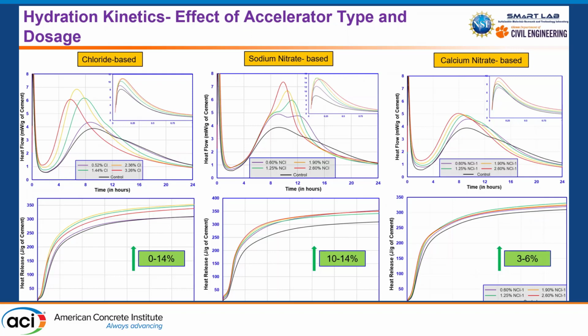So with calcium chloride based admixtures, as seen in literature, they reduce the setting time significantly, or the main silicate peak onset significantly, and they increase the height of the main silicate phase. But what happens is after a certain dosage, you stop seeing this secondary sulfate peak. That is because there are a lot of Friedel salts being formed in the presence of chlorides and other chloroaluminate phases which are being formed in chloride-based admixtures.